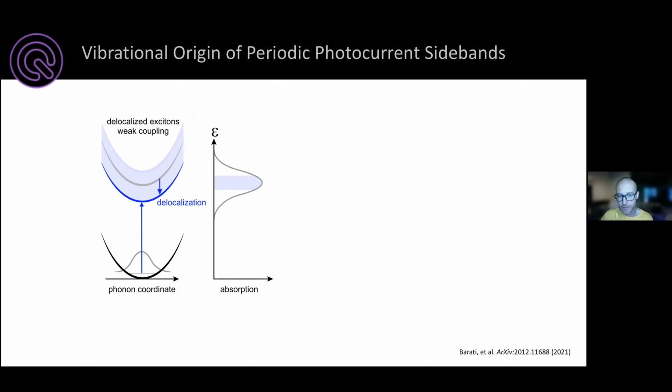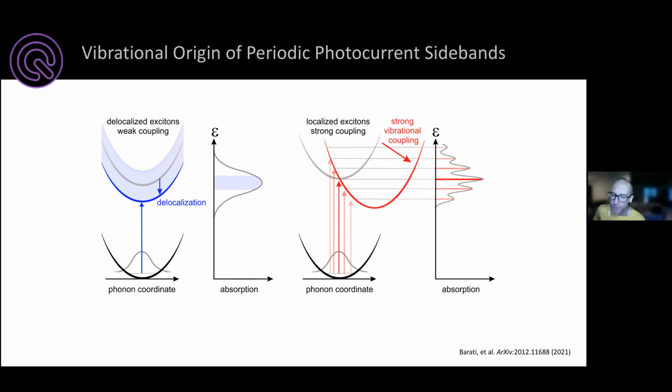And it actually comes from some very, very old condensed matter physics, or if you'd like, quantum chemistry, where we think about vibronic progressions. And one of the origins of these vibronic spectra is the fact that the exciton actually becomes more localized. And this isn't like a smaller Bohr radius. It means that basically the wave functions are becoming more localized. And in localizing, they couple more strongly to vibrations. And so this 30 millielectron volt feature that we see matches very nicely several Raman modes and calculated band structure of the phonon modes in the system.